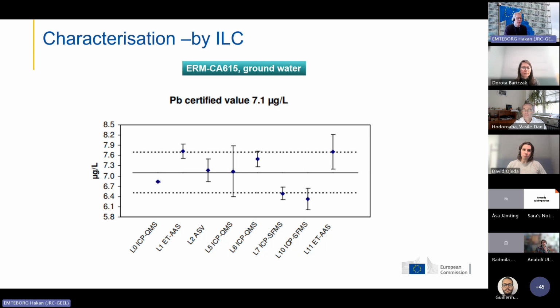What is very interesting with this certified reference material is the characterization exercise, because when we certify a material, we're interested in having as many techniques as possible for the characterization. Here we see that for the characterization and to come to the unweighted mean of those results, it's very advantageous if you can use different detection principles for the actual quantification of lead. So you can see on the x-axis you have quadrupole ICP-MS, you have electrothermal atomic absorption spectrometry, anodic stripping voltammetry, you have again ICP-QMS, and you have a sector field ICP-MS, and again atomic absorption. This is a beautiful example of different detection principles used for the quantification of the same property or same measurand.